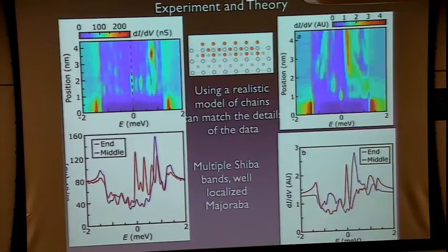And what's interesting is that the one measure that you have here is the size of this peak relative to the background. The data I showed you at 1.4 Kelvin, that peak, if you remember, was way down there compared to the normal state background. Now, routinely at these low temperatures, we start to see these peaks get up, not quite, but almost a factor of 2 above the normal state background.